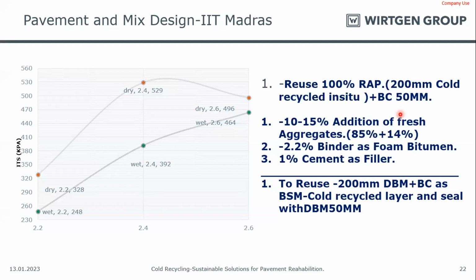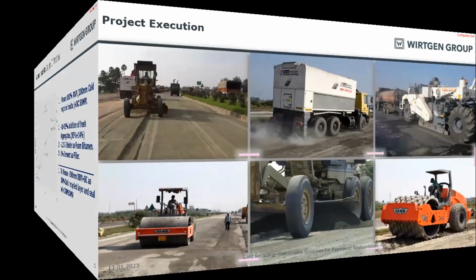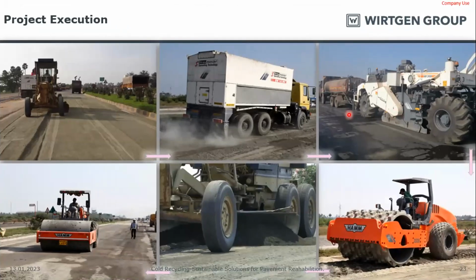So these are some of the values from the mix design. We reuse 200 mm of existing asphalt layer with the addition of 10 to 15% of fresh aggregates, 2.2% of bitumen and 1% cement as filler. So these are some of the job site pictures.